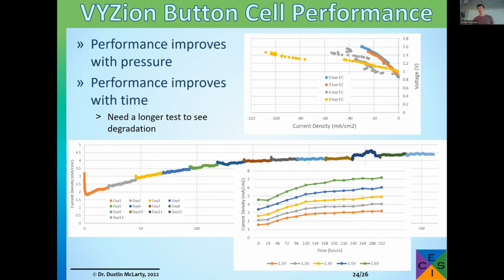So I was going to show a bunch of EIS results, but those are hard to dive into, and some of them give away a little bit more than I'm keen to give away at the moment. So these are just some general results of our new material to show that it is viable. We haven't achieved the level of performance from state-of-the-art electrodes, but we're getting closer. So the chart on the upper right is showing that we did exceed 100 milliamps per centimeter squared at 1.4 volts when we pressurized to 9 atmospheres.